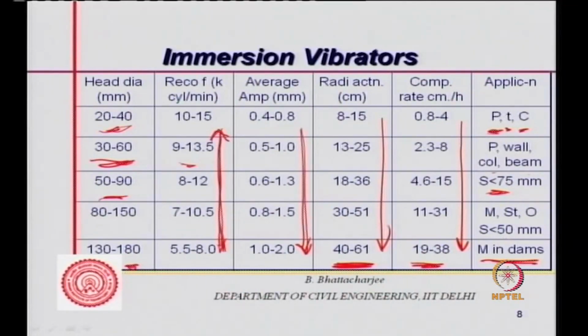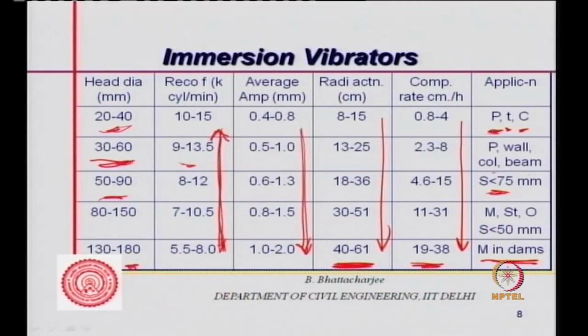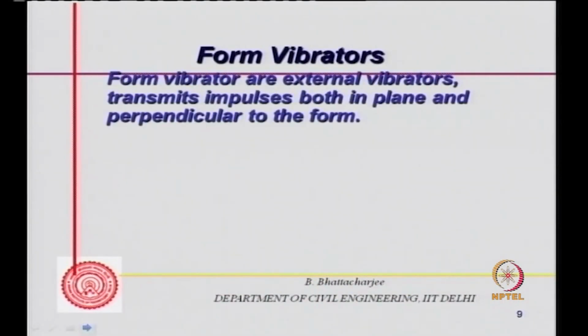Slump less than 50 mm, and this could be on relatively drier concrete, one may use this. So that's how one chooses the needle vibrator. Form vibrators are external vibrators, transmits impulses both in plane and perpendicular to the form.